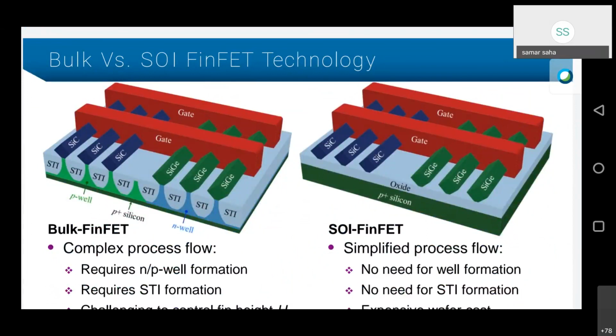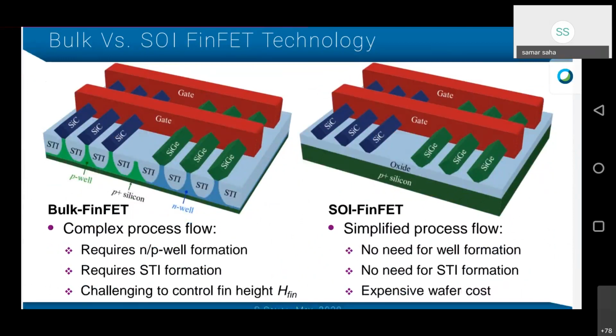So this compares bulk and SOI FinFETs. As I described before, the only difference is the starting wafers. Bulk FinFETs have a complex process flow because they require N and P well formation, and require STI formation to isolate neighboring devices, and so it is challenging to control fin height. Fin height has to be controlled, and there is no etch stop layer to control fin height. But on the SOI devices, it is a simple process. Process flow is very simple. No need for well formation, no need for STI formation. So fin height is very easily controlled because we have STI as the etch stop. Any etching that you are doing will be stopped at STI. So that is easy to control fin height.